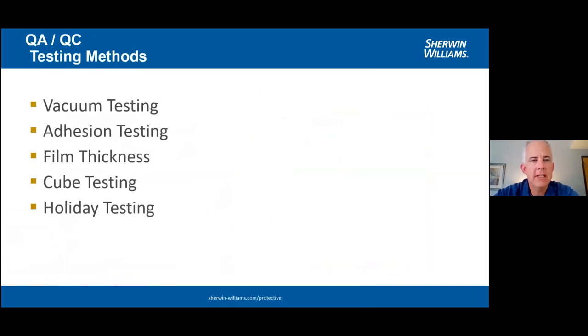A couple of the QA QC testing methods that go on in the sewer collections industry, and I'm just going to mention these. I'm not going to delve too deep into these. The first one I'll speak of is vacuum testing. There's adhesion testing that I recommend doing whenever we do our lining systems and our rehabilitation systems. We do film thickness measurements. We do cube testing of the concrete repair materials to make sure we're getting the structural integrity. And then holiday testing, which is basically making sure that we have a pinhole-free surface whenever we do our chemical-resistant liquid liners in these structures. Holiday testing is the best insurance policy you can have that your applicator has done the work correctly.